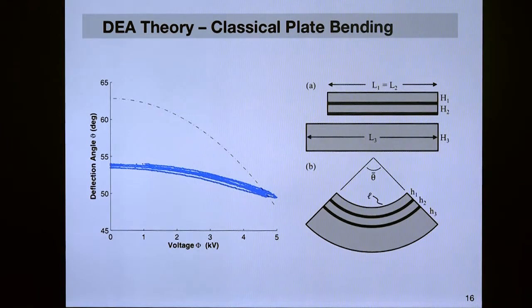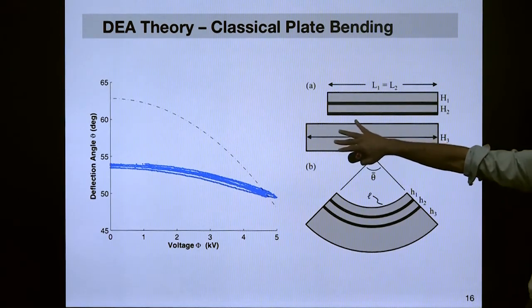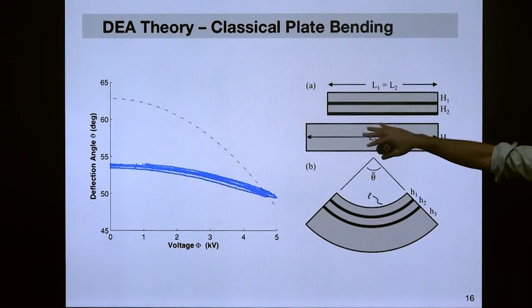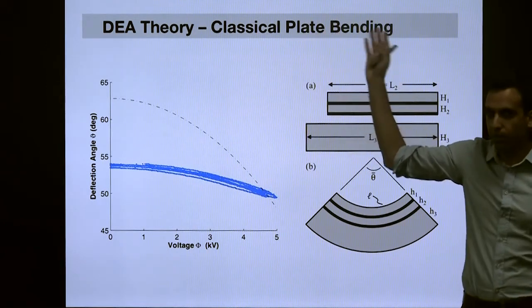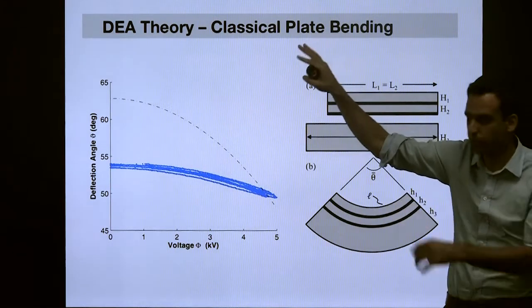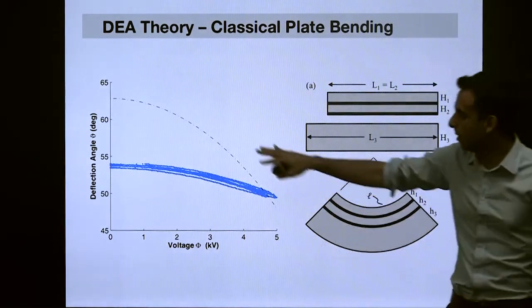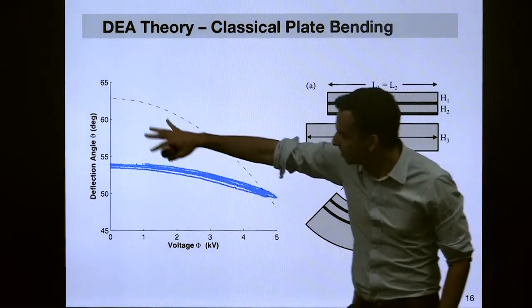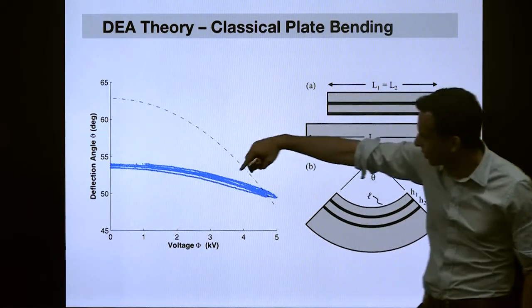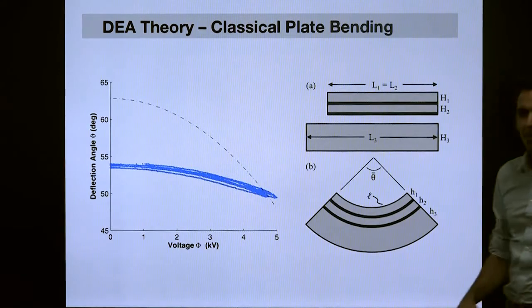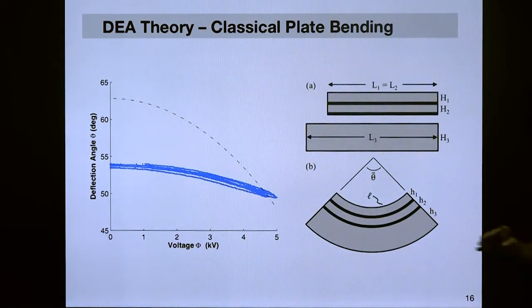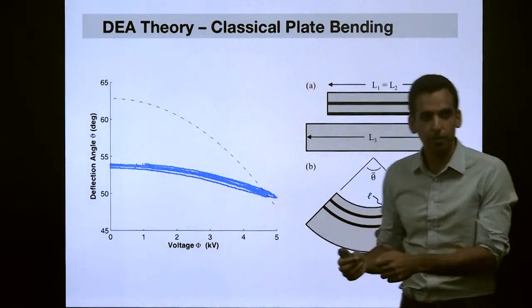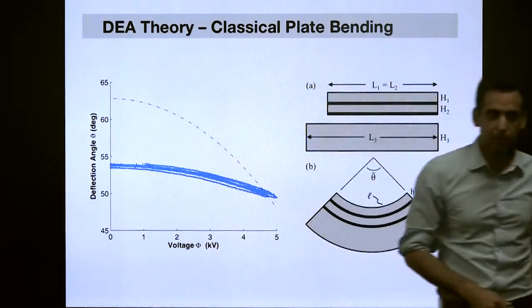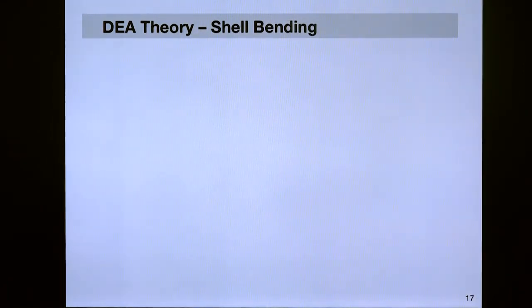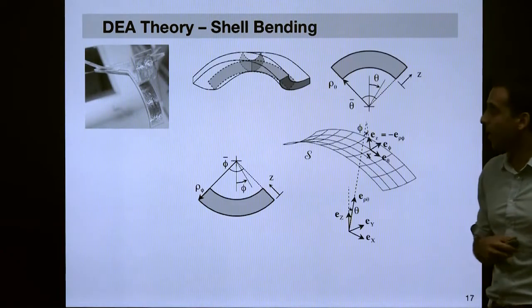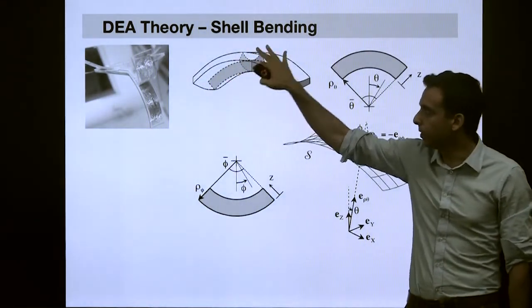Okay, so we did everything right: we know what the material is, we know what all the dimensions are, we know the electric permittivity, shear modulus, all that. We're using just a classical plate bending model. This is also captured by Stoney's formula, and we're just way off when it comes to agreement between theory and experiment. Fine, we're in the same general ballpark in terms of angle of deflection and the voltages at which we'll see responses. So it's good in terms of getting a ballpark, but it's not a good theory in terms of actual operation, and telling us what is that critical voltage that we have to avoid. So if we want to be more accurate and we really want a predictive model, then we have to be very deliberate and a little bit more careful with our kinematics.